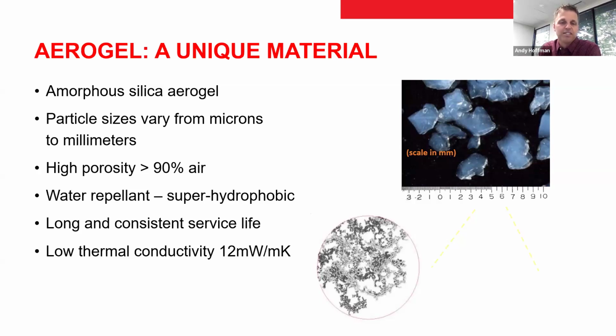And then there's the thermal conductivity again. So remember, lower is better. The thermal conductivity of the raw aerogel particles themselves is about 12 milliwatts per meter Kelvin. To give you a comparison, polyurethane foam is a very good insulator. That's about 28 to 30 milliwatts per meter Kelvin. Calcium silicate, perlite, mineral wool, those are all good insulators. They're about 40 to 45, generally speaking. So it just gives you an idea of just how good of an insulator these aerogel particles really are.